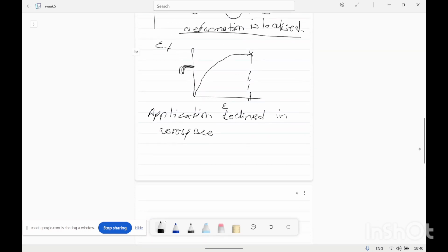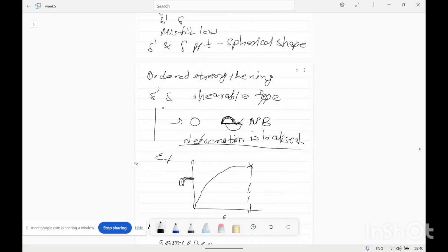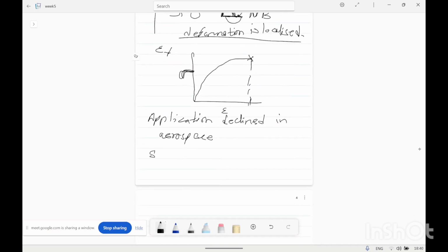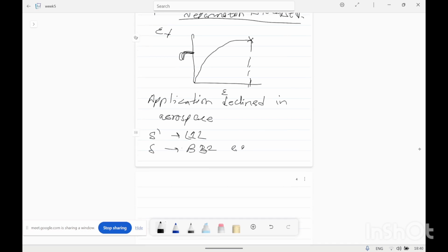This is for the delta prime. The delta prime precipitate has the L12 structure, and delta, which is the equilibrium phase, has the B32 crystal structure, which is found in sodium thallium structure. In the B32 structure, two diamond cubic lattices are interpenetrated.